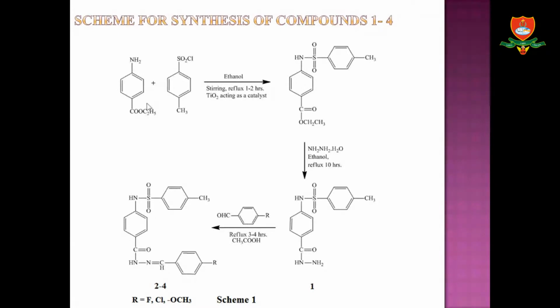Then it is refluxed with hydrazine hydrate in ethanol medium for 10 hours. The substituted carbonyl phenyl hydrazine compound is formed. Then compound 1 is reacted with 3 different types of substituted benzaldehyde for 3 to 4 hours in acetic acid medium. The synthesized compounds 2 to 4 are formed.